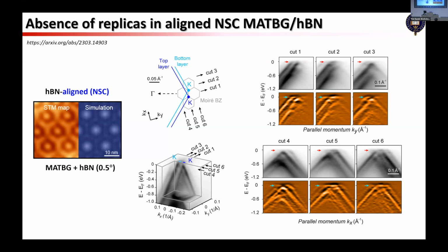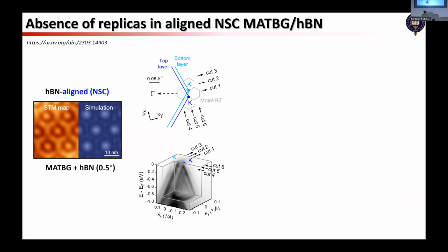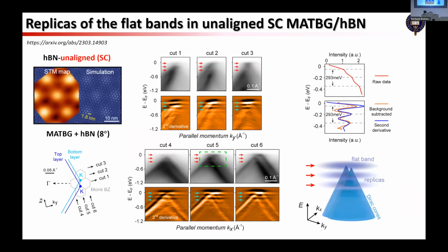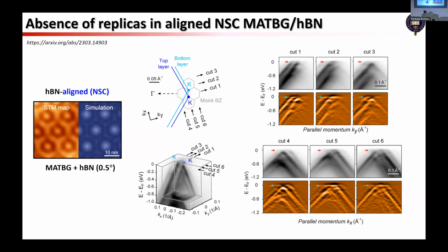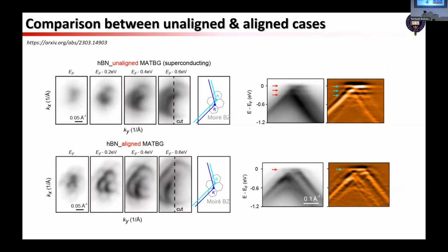There are still some high intensity parts other than the flat band, but you can see that this intensity variation is caused by band hybridization, and because they come from different bands, they don't have this universal energy scale like we saw here. They were all mostly parallel, and here you can see, yes, a Van Hove singularity here and there, but you don't have the universal energy scale. That's the difference, and you can see that they look very different from the unaligned sample.